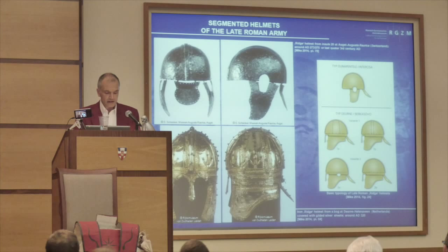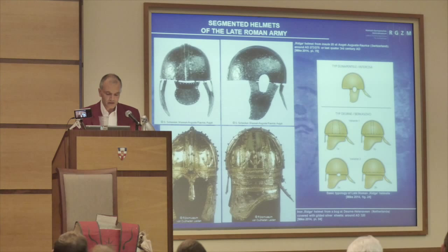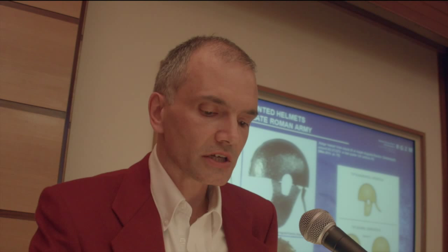On the other hand, a deposit with two small parcels found in the fortress of Ács-Vaspuszta (Joviar) in Hungary consists only of the removed and folded silver elements of an otherwise unknown Roman ridge helmet, thus affirming the usual practice of the helmet's destruction once again from a different perspective. Besides such cover sheets, also constructional elements of nearly pure copper appear on Roman helmets for the first time now. The pure copper used for crest components of ridge helmets was probably easier to handle during the process of fire gilding than copper alloys. The fact that the relatively soft copper is not so resistant against the impact of hostile weapons was less important, given the iron basic elements of the helmet. As the helmet from Augst and other items lost or sacrificed in a vow at Dörner near Kassel around AD 320 illustrate, the two main types of Roman ridge helmets were already in use during the reign of Constantine I (AD 306–337).